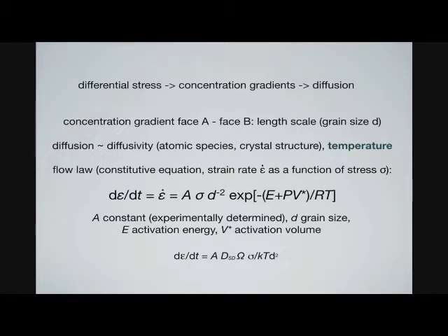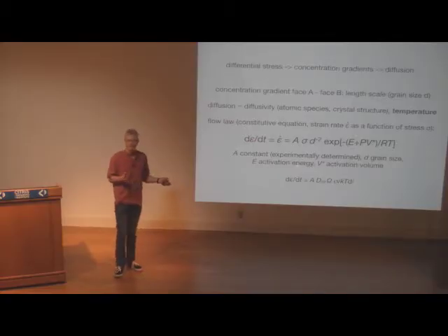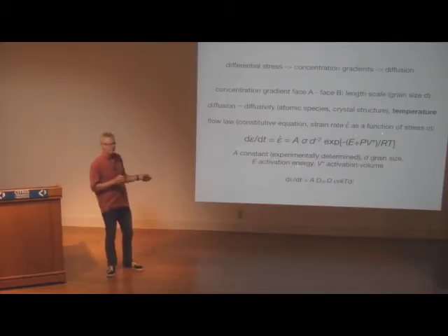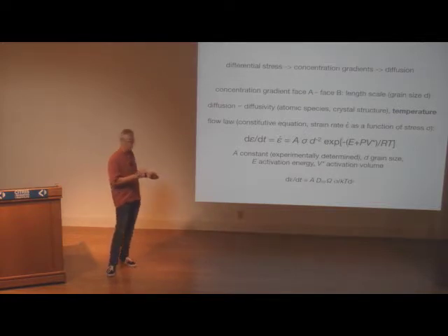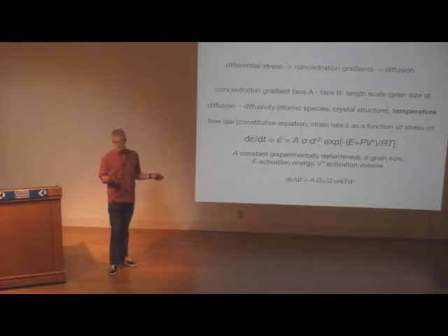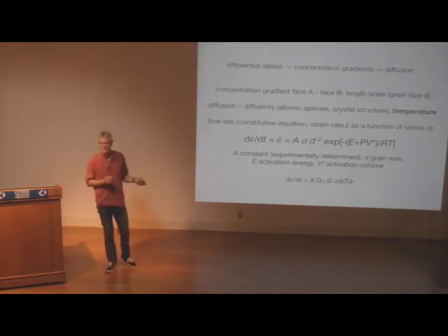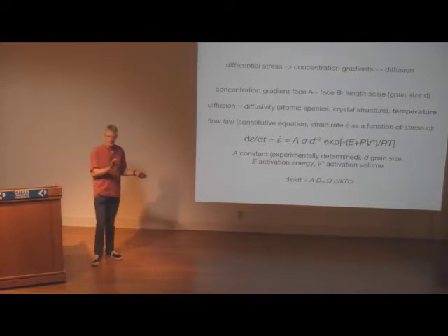So E is the activation energy in this particular case, how temperature sensitive the process is. A is neglected when other parameters are varied. But experimentally, we fit all of this to one set of data. So if you start to change E, then you really have to also start to change A. So A is part of the fitting process of your experimental data, even though it's just this constant.